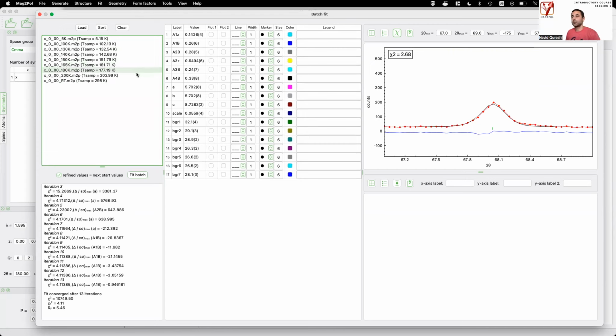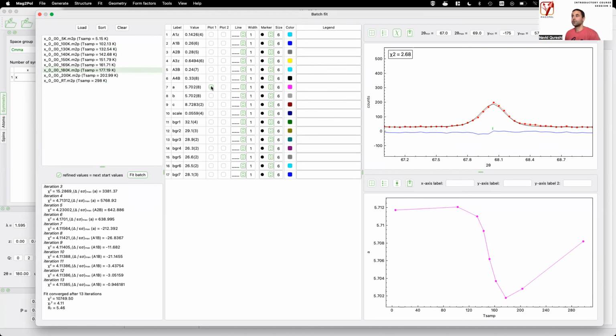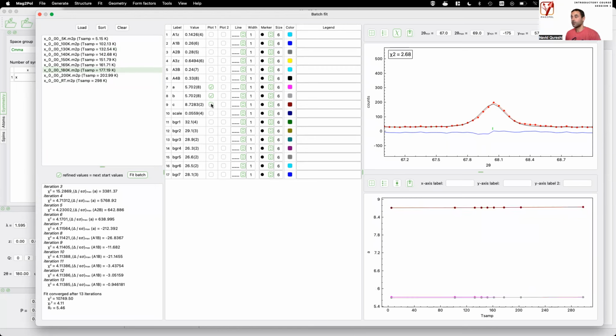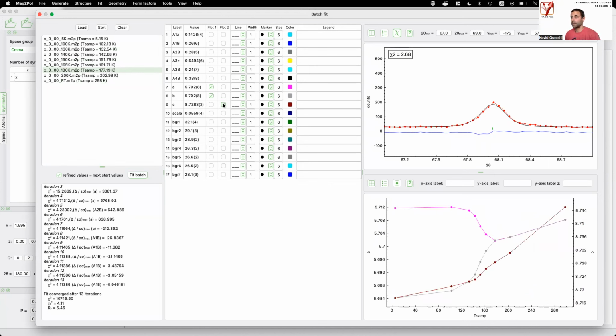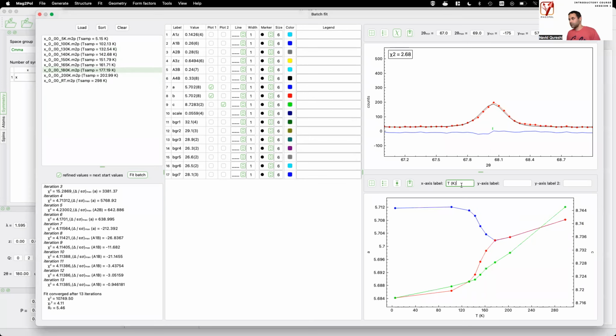And you can directly plot this temperature dependence. So I can click on the A lattice parameter and I click on B, and I can see very nicely how they split from a tetragonal symmetry to an orthorhombic one. I can add the C lattice parameter. Well, now I don't see anything anymore, so I will plot it to the right y-axis. And as before, the controls are very similar. I can change the colors very quickly to make it look a little bit more to my liking. And you can change the labels like this, for example, and that's it. You can export this plot either as PDF or ASCII. So this is a super quick way of doing batch refinement and to look at your results just with a few clicks.